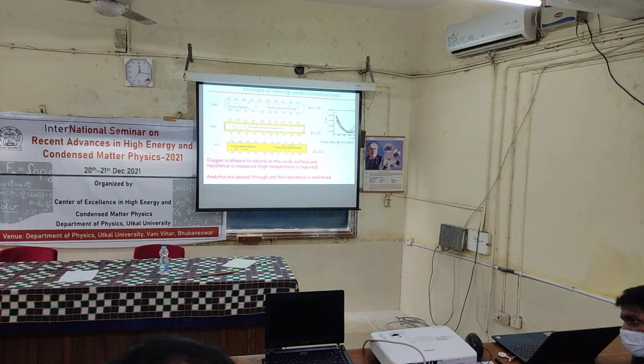And the conductivity changes, or the resistance changes. Now again you do the same exercise. You pass analytes of the reducing gas, and you get back your resistance. In presence of oxygen, we have one resistance. Now you pass the reducing gas, we have another resistance. Again in this case, the change in the resistance gives you the concentration of the reducing gas present in the system. The only difference here is that this is possible at room temperature. And to some extent we have achieved that.